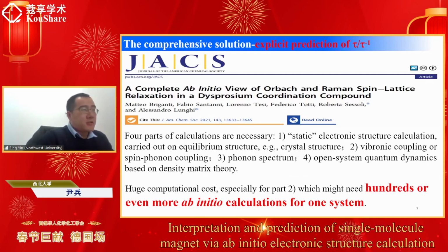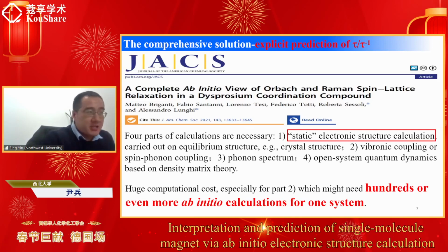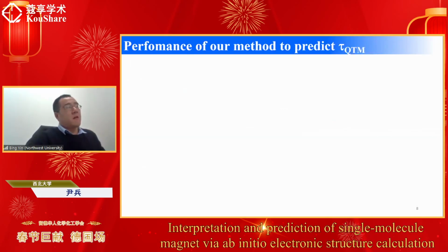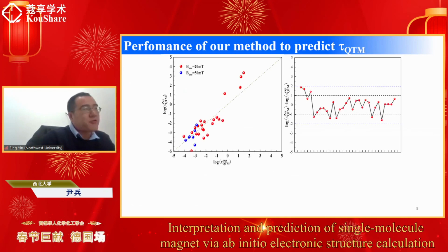What our small group wants to do is to give reasonable interpretation and prediction based just on static electronic structure calculation carried out on the crystal structure. With the equations proposed by us, and the current highly accurate ab initio calculations based on CASSCF, with, for example, the MOLCAS code or OpenMolcas code, we can calculate the parameters of many systems, and the theoretical predictions show good agreement with experiment. Generally, in more than half of the systems studied by us, we found the deviation between theory and experiment is less than 1 order of magnitude, and deviation larger than 2 orders of magnitude is rare.